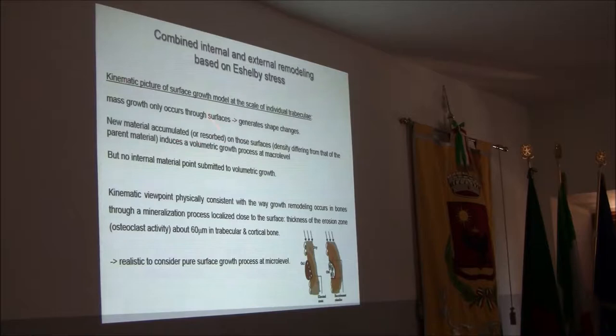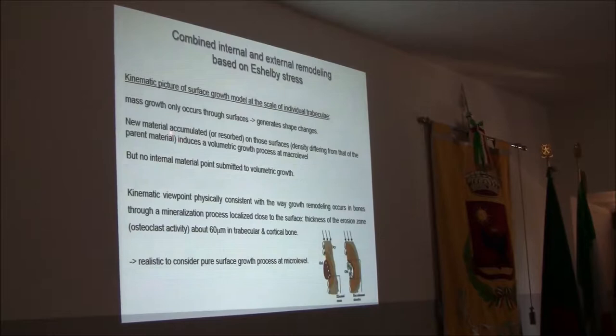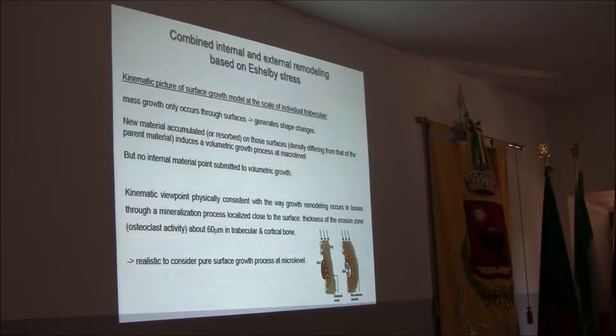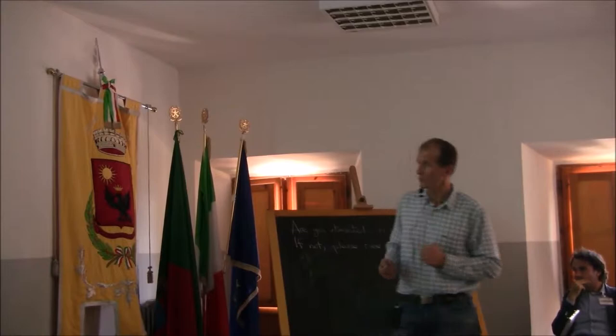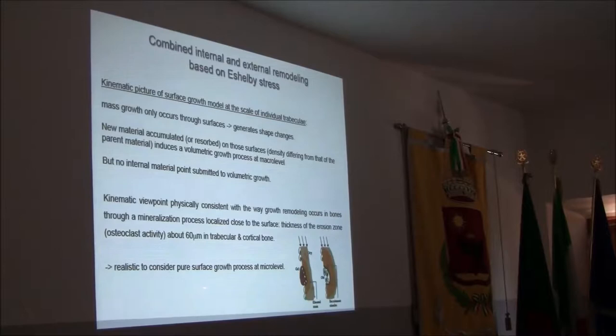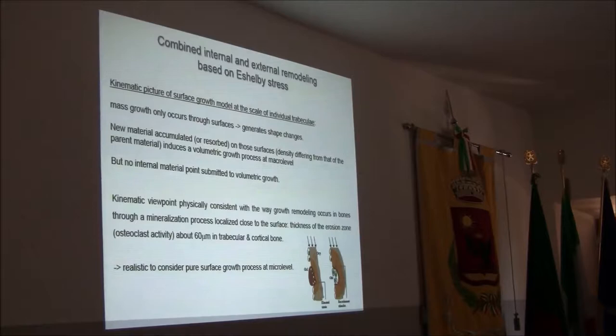Due to the fact that the newly accumulated material — the mineral — may have a density different from that of the bulk parent material, this will introduce internal strains and residual stresses, and will also lead to the phenomenon of volumetric growth, which is the apparent phenomenon noticed at the macroscale but due to a surface mechanism. This kinematic viewpoint is physically consistent with physiology, and it is realistic to model a pure surface growth mechanism at the micro level of individual trabeculae.